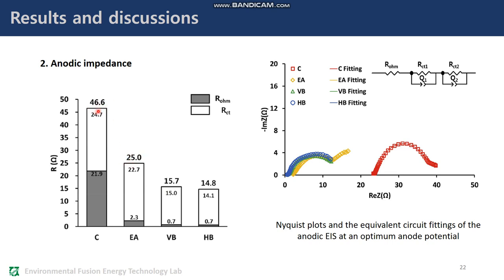The brush anodes had 1.6 to 21.2 ohms lower ohmic resistance, 7.7 to 10.6 ohms lower charge transfer resistance, and 9.3 to 31.8 ohms lower total anode resistance than those of the carbon cloth anodes. Anodic ohmic impedance in total anodic impedance was 47% in C, 9.2% in EA, 4.5% in VB, and 4.7% in HB for each condition.